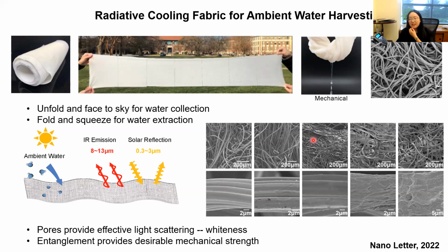This fabric, which is mainly cotton fibers inside, features a multi-scale arrangement of the fibers. As you can see, we have the micron-scale fibers, and each fiber is further composed of aligned nanofibers inside. They feature a mesoporous structure, so that's the reason why it looks very white. And we want the whiteness for effective radiative cooling performance. All these entanglements that you are looking at in the SEM provide desirable mechanical strength, so it can sustain many cycles of water collection and extraction by mechanical squeezing.